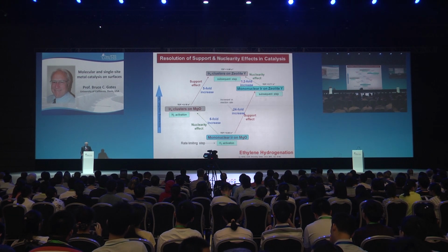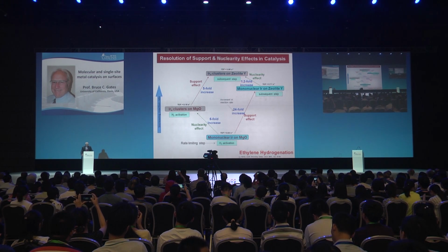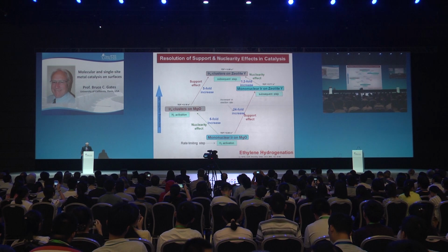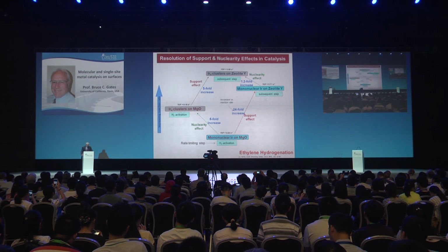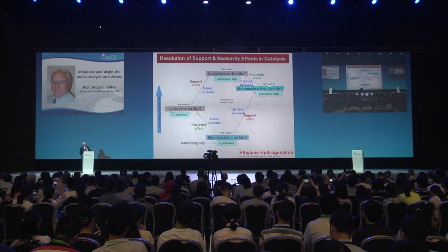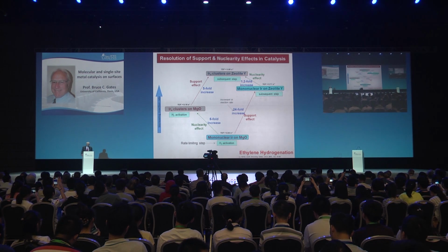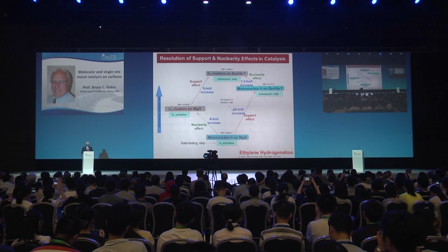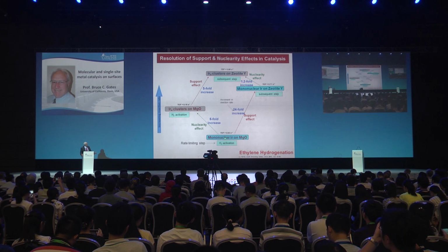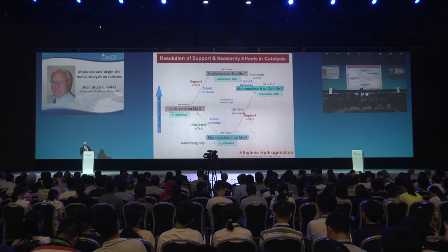Let's look at a nuclearity versus support effect. So mononuclear iridium on MgO, let's change the support, otherwise having the equivalent sample. You see the activity goes up. This is a good electron donor support. That's a poor one. This is a more active catalyst.